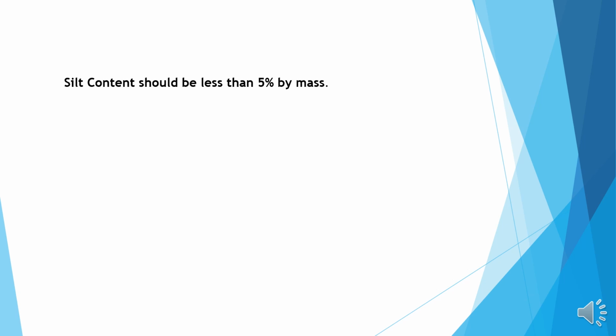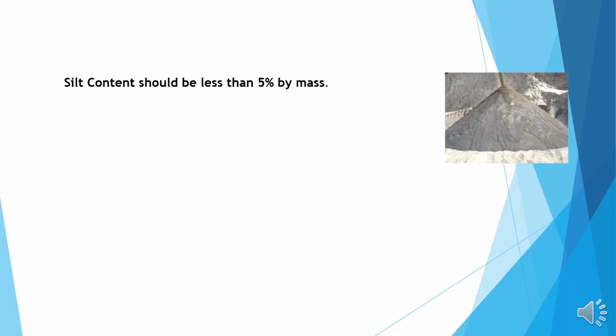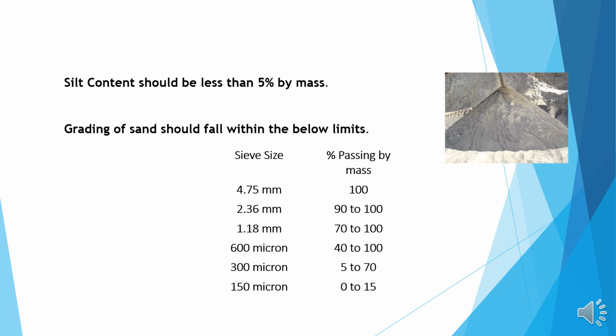Silt content should not be more than 5% of the mass. See, this is crushed sand. The silt content should not be more than 5% by mass. Grading of the sand should fall within the below limits. Sieve sizes: 4.75 mm 100%, 2.36 mm 90 to 100%, 1.18 mm 70 to 100%, 600 micron 40 to 100%, 300 micron 5 to 70%, 150 micron 0 to 15%. Relevant IS code is IS 2116.